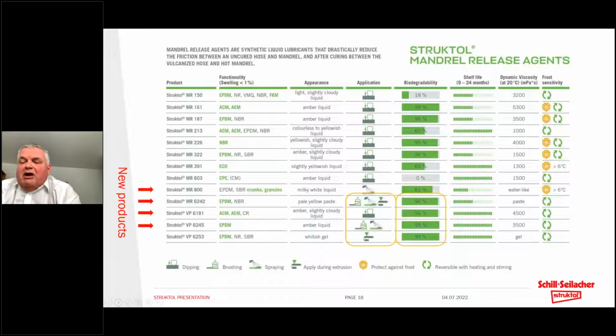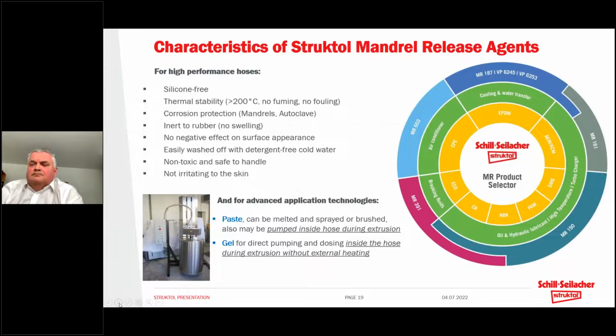Also, these products should be biodegradable. The hoses have to be washed after production to remove the release agent, and it's much more preferable to have a biodegradable, easily water washable product so that the washing water can be disposed of as normal water and not treated as a classified wastewater. So the degree of biodegradability should be as high as possible in order to perform well with such a product.